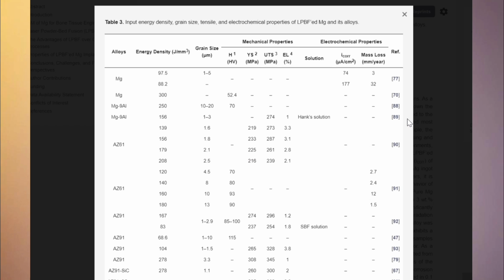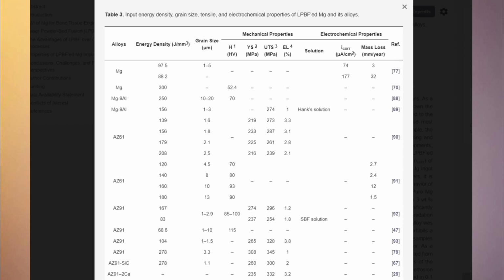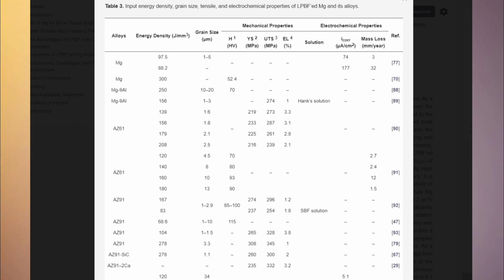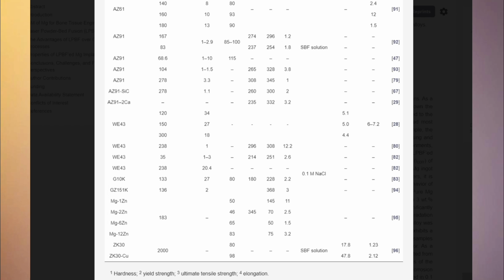So let's go to table 3. This table presents a comparison of LPBF-processed magnesium and its alloys. Energy density varies significantly, as you see, across different magnesium alloys, and definitely influences their properties. As an example, the AZ91 alloy demonstrated superior tensile strength but less ductility compared to the other variations. Pure magnesium exhibits higher corrosion rates than some of its alloys. Overall, the mechanical properties improve with alloying, with AZ91 displaying some of the best mechanical performance among the materials tested. This table, if you notice, also illustrates how different processing conditions substantially impact the resulting properties of identical alloy compositions. This data is based on different studies in different years and countries.